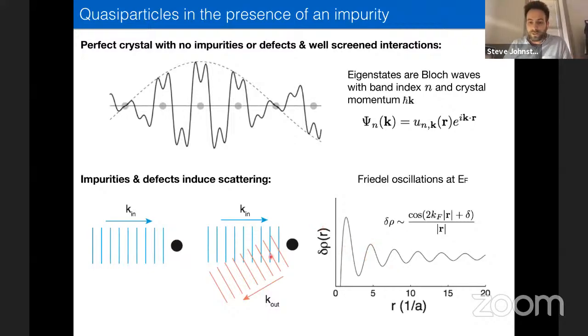What's important here is that, when you do this for single free-electron-like band structures, what you find is that the far-field image, these wavelengths out here, are really dictated by twice the Fermi wavelength. This comes from the fact that you're dominated by backscattering processes where you go from k_F to minus k_F. And so the momentum change is 2k_F.